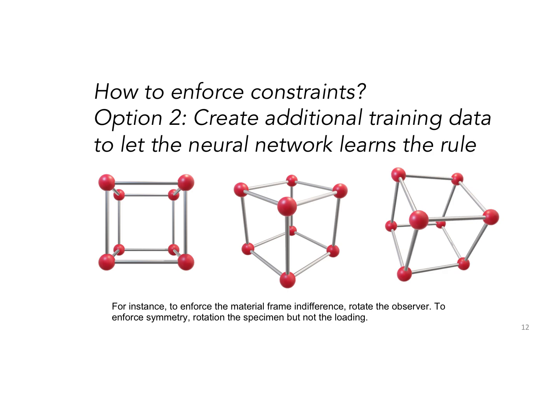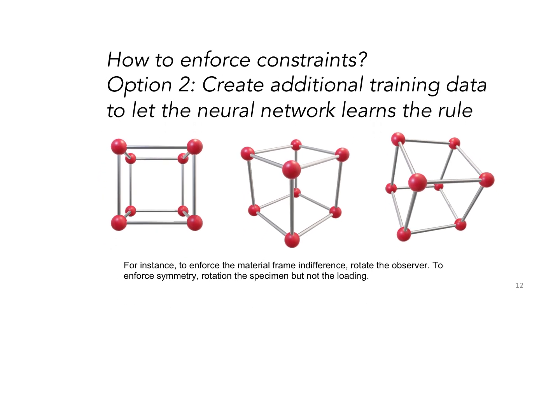Let me give an example. Say this is for rotations. I have the stress, but I only have a device that does a true triaxial compaction test. So I will have epsilon 1, epsilon 2, epsilon 3, and no off-diagonal term. I have a lot of those data, but let's say the material is isotropic, so I will only have diagonal terms. But it doesn't mean that the material is always in the principal stress. It's the tests you have that are in the principal axis.